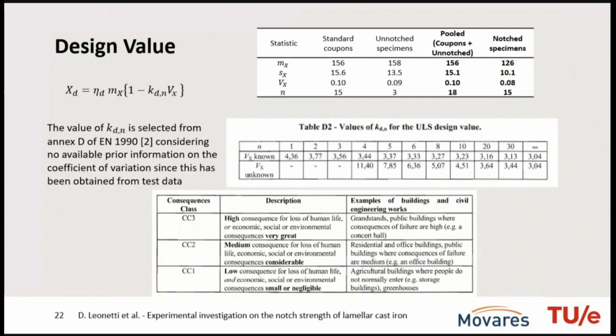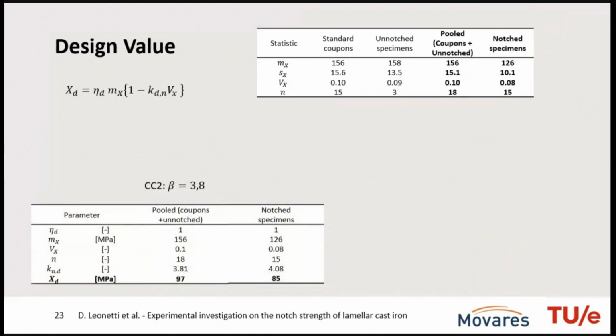In the end, we needed to decide which consequence class to apply to this structure, depending on essentially the consequence of failure. Normally, railway canopies, this kind of small structure, are public structures, so they would fall in consequence class 2. You can imagine consequence class 3 would be for a bridge, something like that. So consequence class 2, okay, it could be busy, but it's not the biggest train station. Nevertheless, I will show you the calculation for both and then explain why we went for consequence class 3 instead. So for consequence class 2, the reliability index is equal to 3.8.